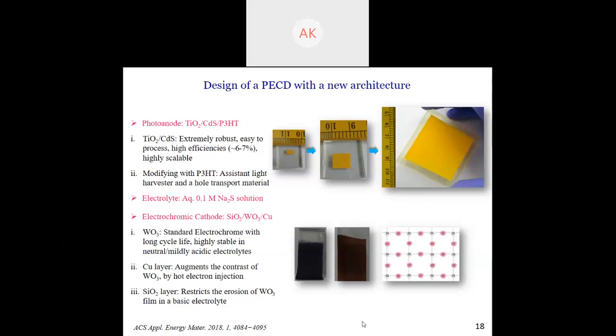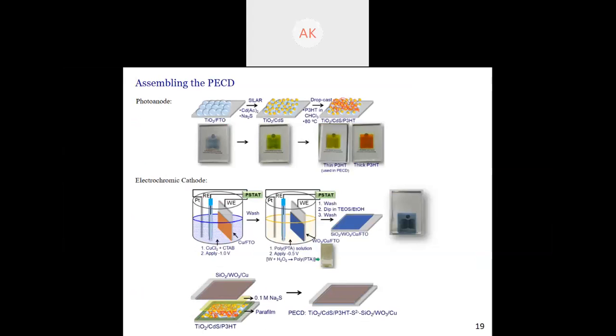I'm not very clear, but I can show you this. Suppose you have a TiO2 film, it is white in color. It is generally not transparent; I have made it for transparent. It's a white color film. When you start growing CdS, you can see the color changing to pale yellow and then deep yellow. Then there are characterizations we go for: XRD, SEM, TEM, to check the sizes and how much CdS layer thickness. We go for cross-sectional SEM images to check the thickness of the TiO2 layer and then the CdS layer on top of that. So, did you go for these characterization techniques?